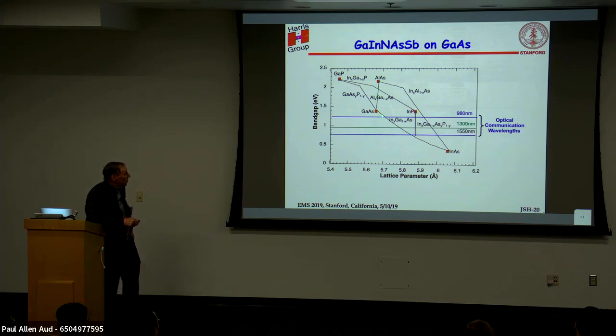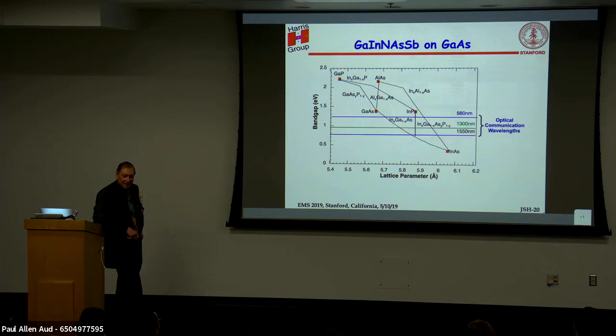but it wouldn't work out here where ultimately people needed it for optical communications. And so all of that is done with indium gallium arsenide phosphide. And so there's a delicate balance. If you change the indium to gallium ratio, you also have to change the arsenic to phosphorus ratio to stay on this line. So it just took a lot more sophisticated technology to do that. But when people get desperate enough, they solve the problems, and engineers are pretty good at that, and that's been the history of engineering.